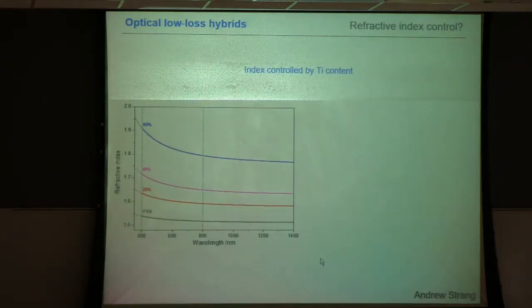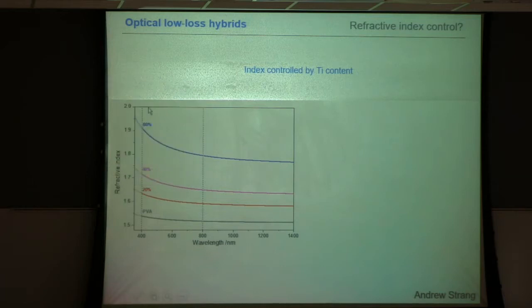The first refractive index. So we did ellipsometry, and you see already, not surprising, the higher the material's content, going from neat polyvinyl alcohol, 20%, 40, and 80 volume percent of titania. We increase the refractive index. What is pretty unusual is we have a low dispersion. So it means that the refractive index doesn't really change with wavelength. This indicates already that we only start to have absorption over here. So it sort of supports already the idea that we have a very low absorbing material.